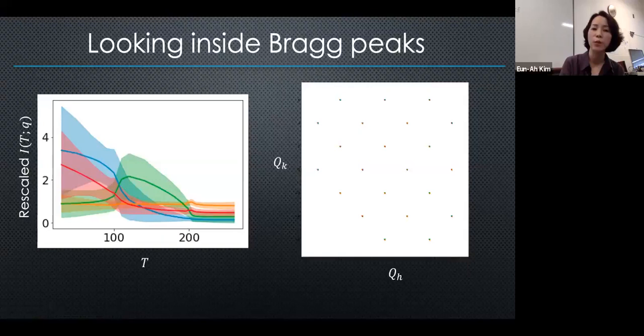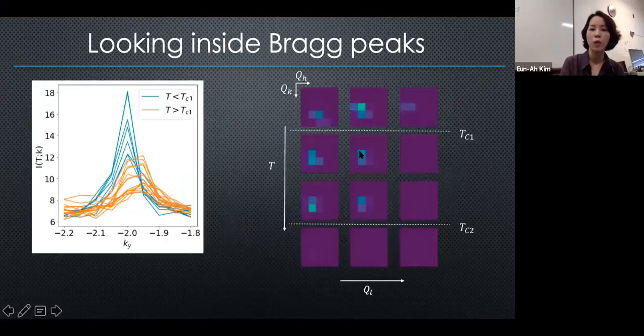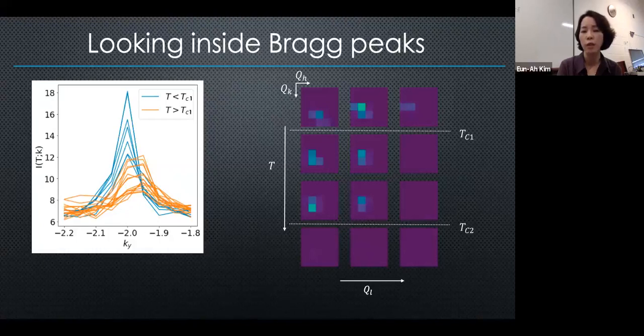And we were really puzzled for a while. Eventually, though, we were able to understand what was going on because the algorithm pointed us to where to look. So now since we've been told that there is something happening inside each Bragg peak, we just looked at it. This is the raw data. And we found, indeed, what's happening is the Bragg peak has a little bit of a width, and that shape is changing. This shift of the weight is clearly coming from the intra-unit cell distortions that are giving this chirality.